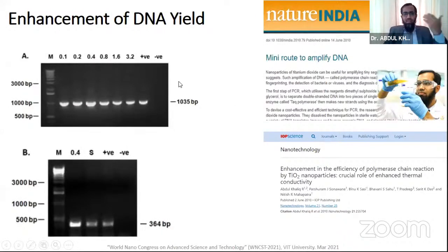In this result, what you see is that with an optimal concentration of nanoparticles, you can amplify or enhance the yield of PCR. This is a positive control without any nanomaterials incorporated. Subsequently, when you keep increasing the concentration of nanoparticles, the yield increases. But as the concentration is increased, we are also required to take note of the specific heat, as the specific heat is going to determine the fidelity of the reaction. The more nanoparticles you add, the more the specific heat increases. That will affect the fidelity of PCR itself. So the optimization process is extremely critical, and we determine that.